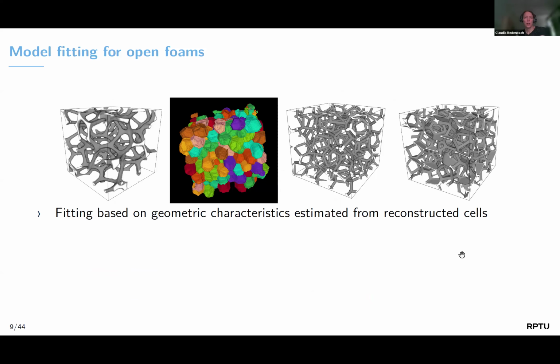How does the modeling chain look like? So initially here, for instance, we have an open cell foam. To describe the cells which are initially not really visible, we have to reconstruct them in the image using a watershed transform. So that happened here. Then we would fit a Laguerre tessellation to the observed cell system. We would take the edges of the tessellation cells visualized here, and then we would suitably dilate them to kind of attach material to the edges.